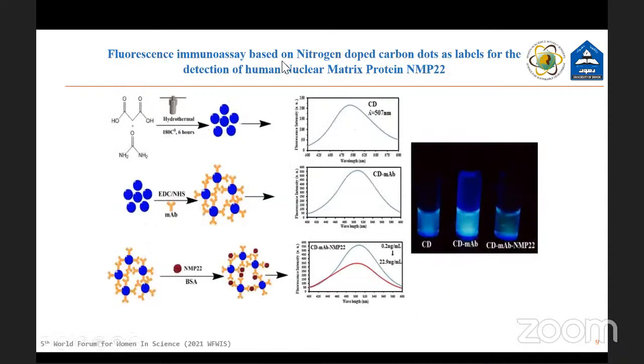Fluorescence immunoassay based on nitrogen-doped carbon dot as label for the detection of human nuclear matrix protein. First, we synthesize our nanoparticle from citric acid. We mix citric acid with urea, and we put it in an autoclave at a temperature of 180 centigrade for 6 hours.